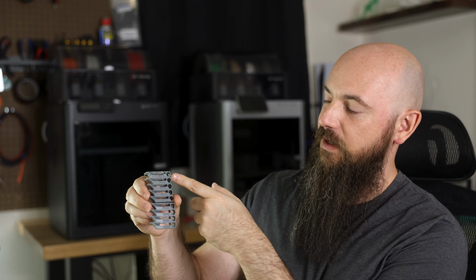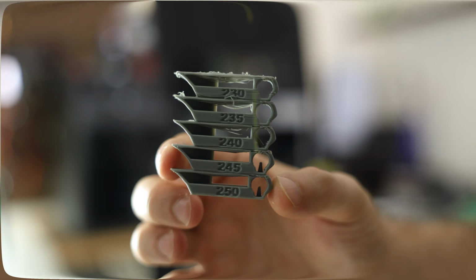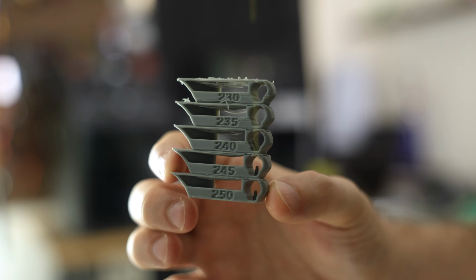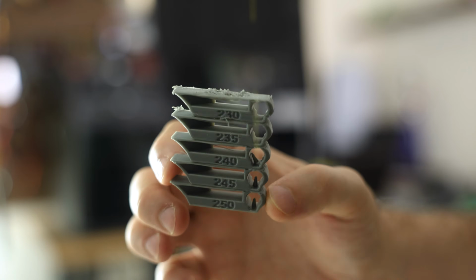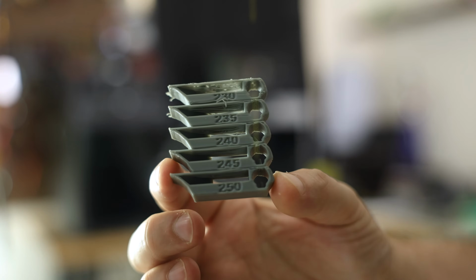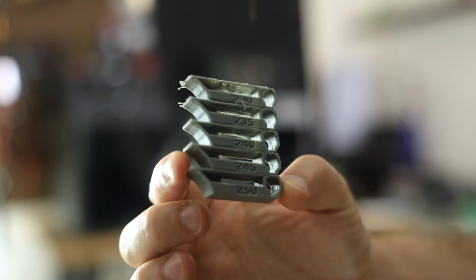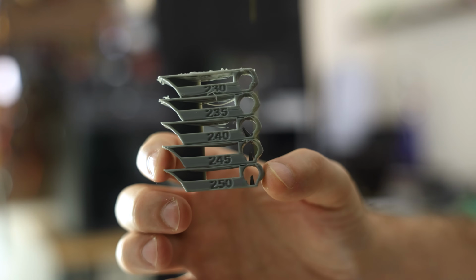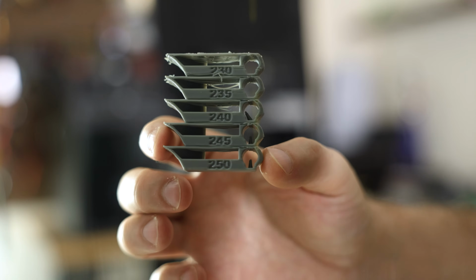The temperature tower is a set 3D printed item that's stacked on top of each other with an incremental change in temperature. This is the temperature of the extruded material from the hot end. In this case, this was printed with PETG on the X1 Carbon at 230 degrees. It was barely hot enough to come out, and it was clumping as soon as it was coming out of the hot end. That's why this top surface is very rough, and there's lots of stringing and globs, and it doesn't look very good.